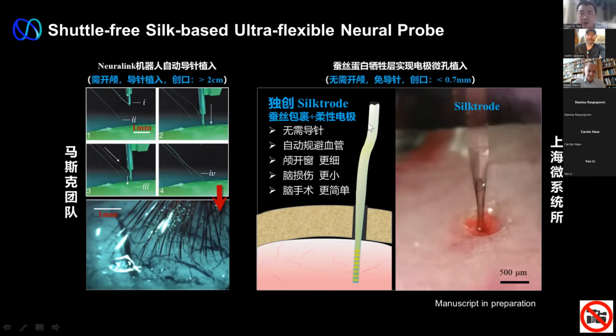But in our case, we can finely tune the mechanical properties of the silk-coated flexible probe so that it sits nicely between the very soft brain tissue and the slightly harder blood vessel. So we only need to open up a very tiny hole, only bigger than the probe itself. It's sub-millimeter; we only open up a 0.5 millimeter hole. We can do that regardless of whether there's a blood vessel right at this implantation site.